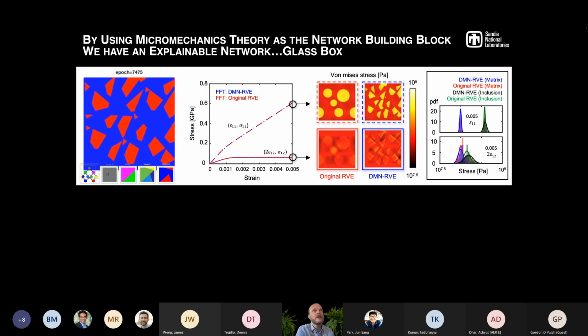And so what you see on the left-hand side of your screen is a representation of the network. All the nodes and the information that's being carried by the nodes, we can translate that into an equivalent learned microstructure by the network. And what you see is that very rapidly during the training, the network is going to start to converge towards some fairly complicated microstructure, which it thinks is the equivalent RVE from the original RVE.